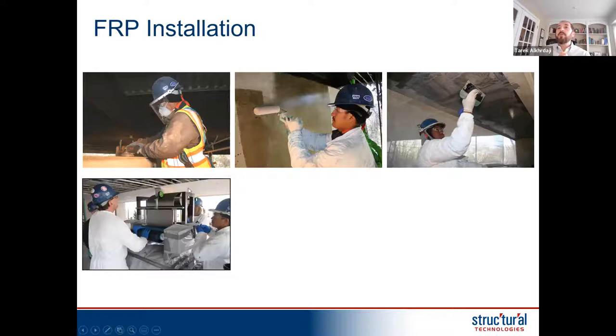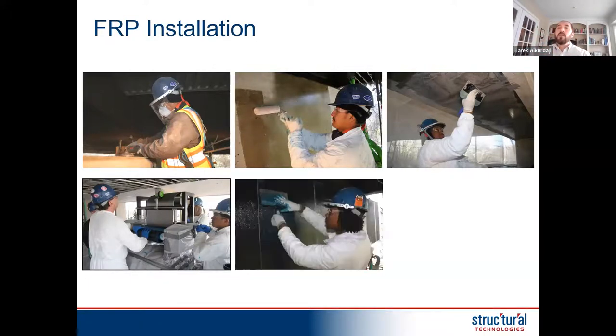Next step, you bring in the carbon fiber, which comes in rolls of different widths, 300 millimeters, 600 millimeters, depending on the product. You put it in a saturator machine, and that saturator has in it a resin, really an epoxy bath. So the fabric gets into that epoxy bath, and there are several rollers that roll in and push the epoxy into the fabric. The idea is we want to make sure it's fully saturated with epoxy, so it doesn't have any dry spots or dry pockets within the fiber itself, because that would prevent the forces from transferring within the fiber. So these fibers are continuous, long fibers of carbon. They're creating like a micro rebar, and you encapsulate that into that epoxy to create that composite that is glued into the concrete.